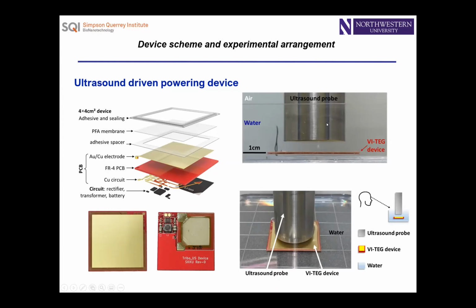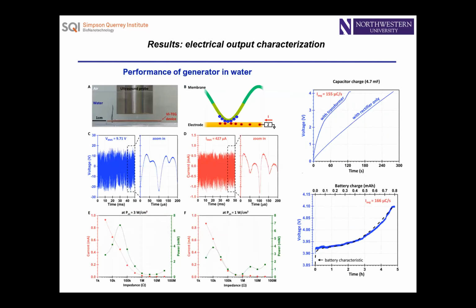At the beginning, we tested our device in a water environment because ultrasonic attenuation is close to zero in water, so we could transmit as much ultrasound as we can. We used ultrasound at 20 kilohertz, which is an inaudible sound. Generally, in the triboelectric nanogenerator research field, we measure the electrical output voltage and current. About 10 volts of voltage and 427 microamperes of RMS current were detected, measured with a 4 by 4 centimeter square device.